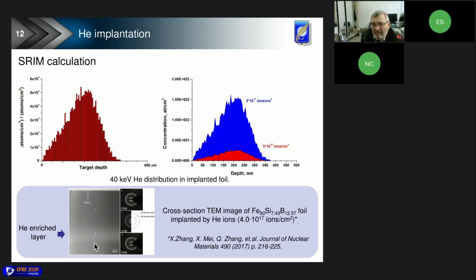In our case, the maximum concentration of helium atoms inside the foil can be estimated knowing the approximate atomic density of the film. So this value at this dose is just about 15 atomic percent. This helium content maybe is not enough to form visible blisters. At the same time, we can stimulate their formation by stimulating diffusion processes.